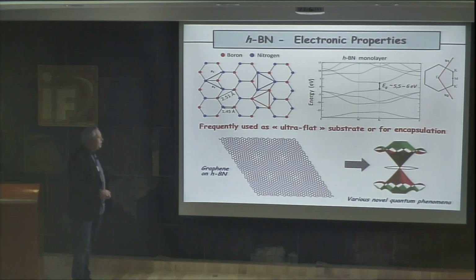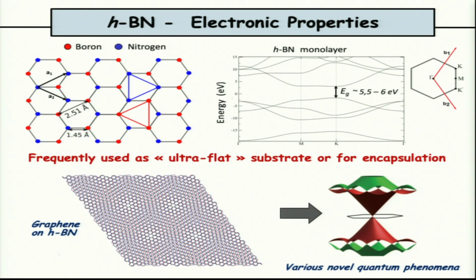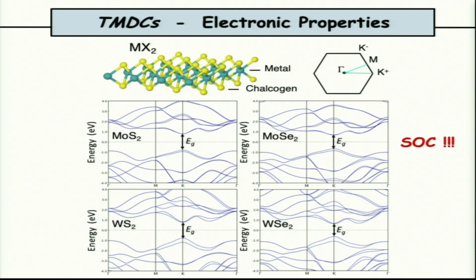However, when you put it on hBN, you have this moiré structure that you can see here. So a kind of superlattice that appears. This is because, in fact, you do not have exactly the same lattice constant in the two structures. So you have 2.46 in graphene, and you have 2.51 in BN. So you have about 1% of difference. But this leads to this superstructure, which can lead to very interesting electronic properties, and various novel quantum phenomena have been observed, like, for example, the fractional quantum Hall effect, and also the Hofstadter butterfly, for example, which had never been observed before in a solid-state system.